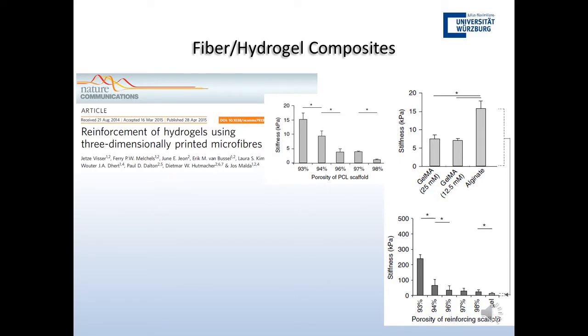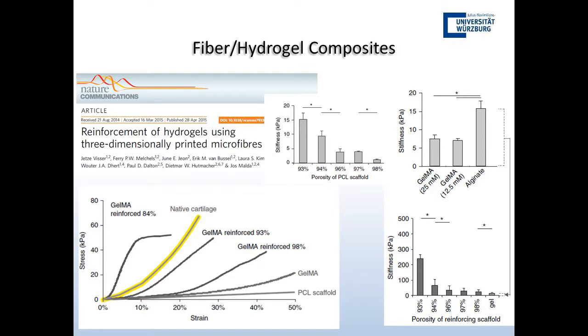I think one of the things that put it on the map for many people was this paper, which showed a really interesting physical effect that we saw, where if you have a melt electrowritten scaffold that's 93% porous, it has a stiffness of about 15 kilopascals. And if you mix that with a matrix, so GelMA, which has a stiffness also of about 10, 15, or alginate, we're getting stiffnesses now of about 250 kilopascals, so a 54-fold increase in strength.